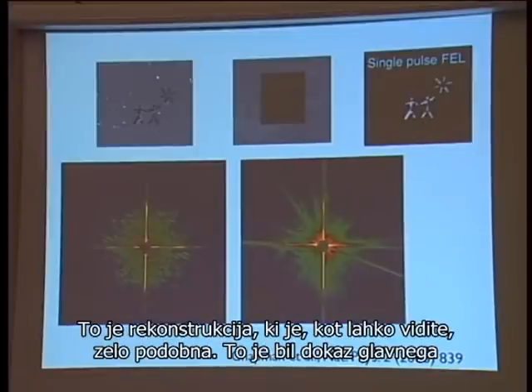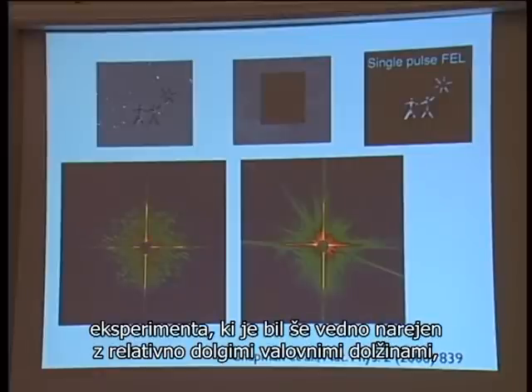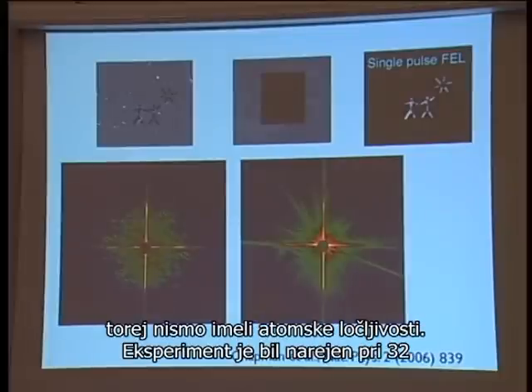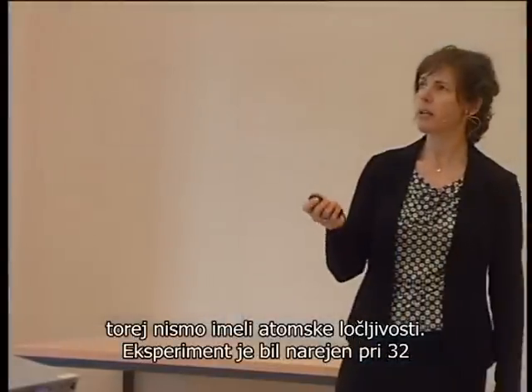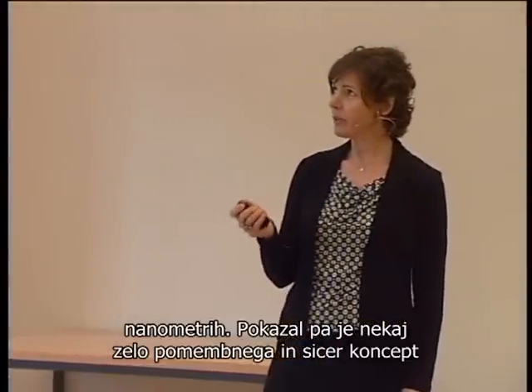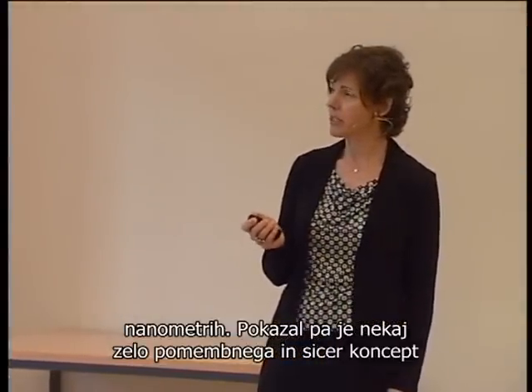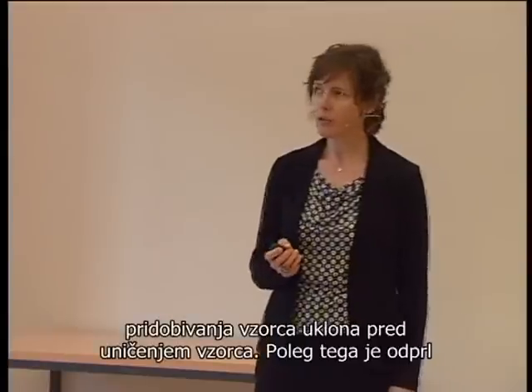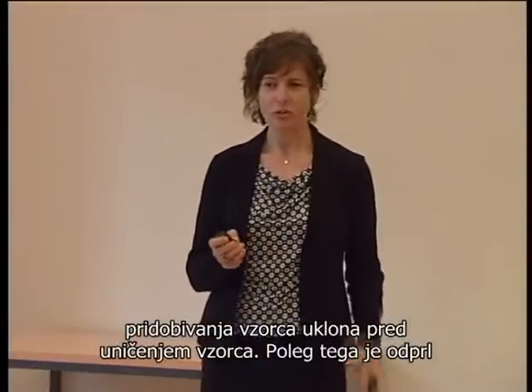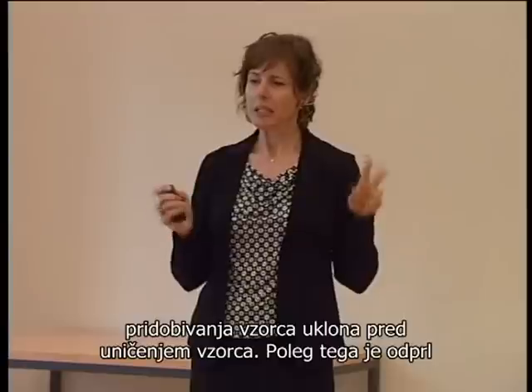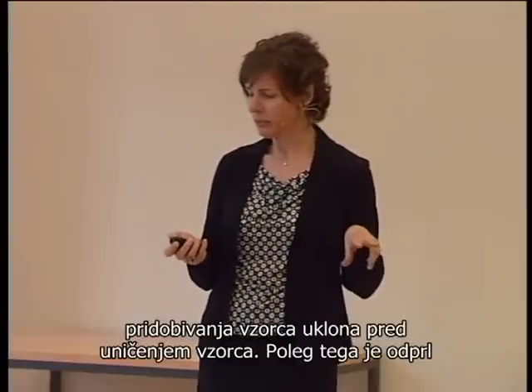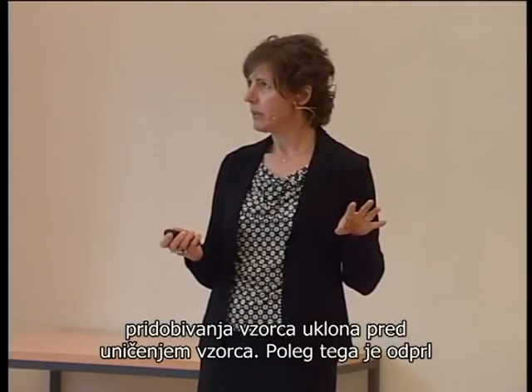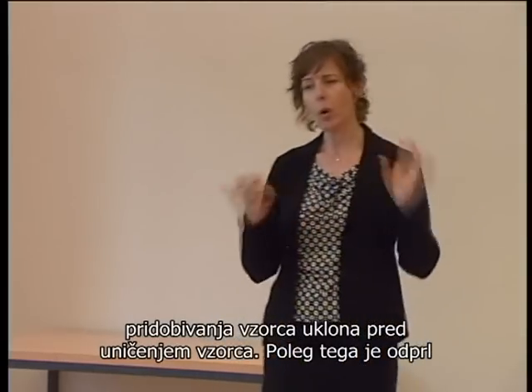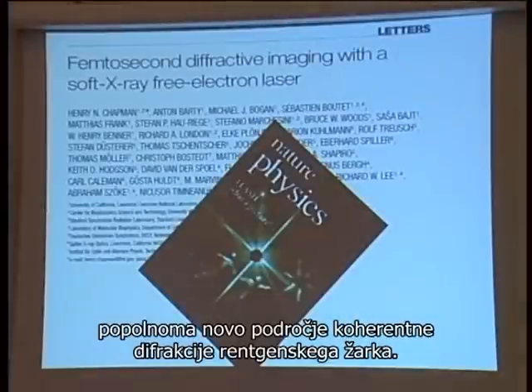So this was a proof of principle experiment, still done at relatively long wavelengths, so we don't have atomic resolution here. The experiment was done at 32 nanometers, but it demonstrated a very important thing, that we were actually able to obtain X-ray diffraction before destruction. It's the so-called diffract-before-destruct concept that everyone uses now. It demonstrated that, but also opened a completely new field of coherent X-ray diffraction.